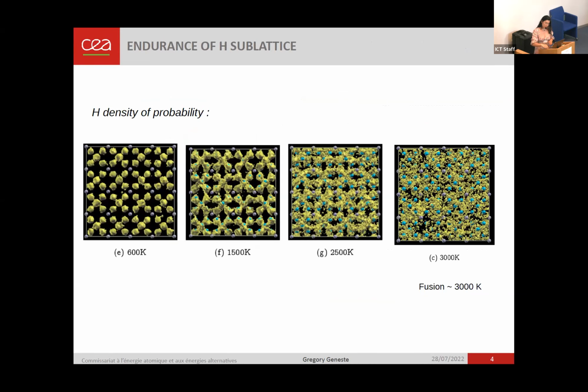Another beautiful result of this study is that the hydrogen doesn't diffuse randomly. They diffuse on the H sublattice. Here is the hydrogen density probability for different temperatures. At 600 Kelvin, there's no superionicity. The hydrogen doesn't diffuse, and we can see that the density of hydrogen is placed on the sites of the sublattice. And when it becomes superionic